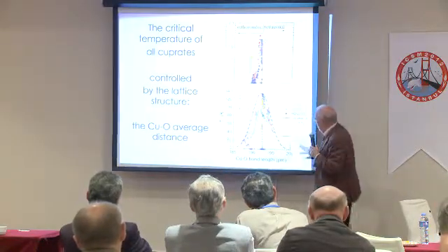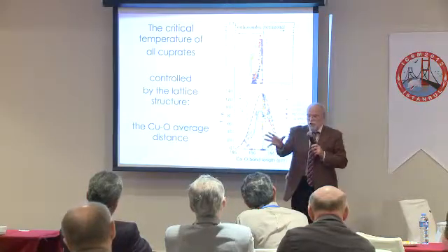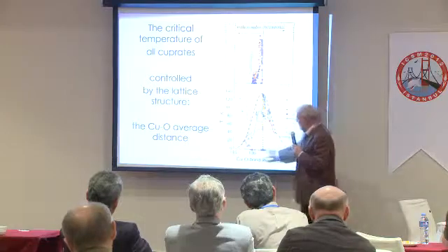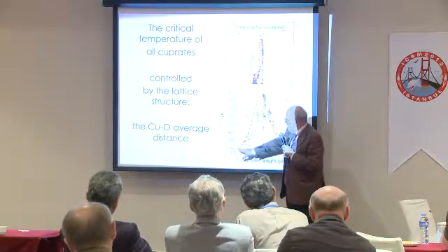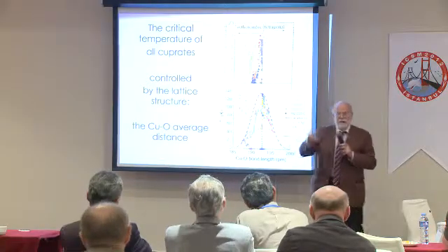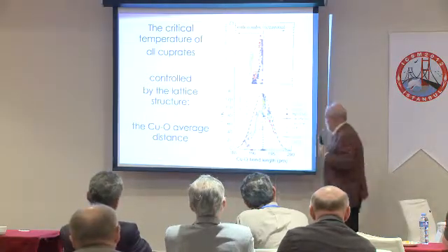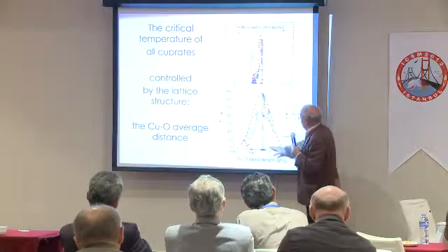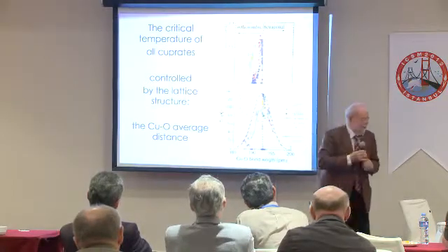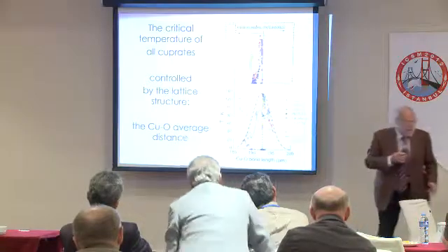Then it's clear that the module of the copper-oxygen lattice is compressed, nothing below 1.85. So too much compression, there is no agreement. They cannot have compensated structures. And then you see that you have one optimum compression that makes the highest Tc. It's the most fundamental.